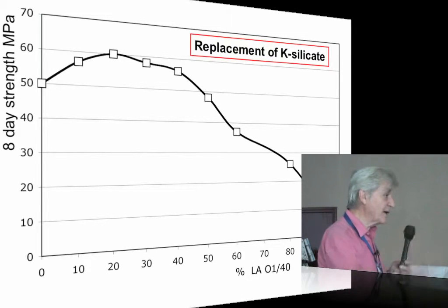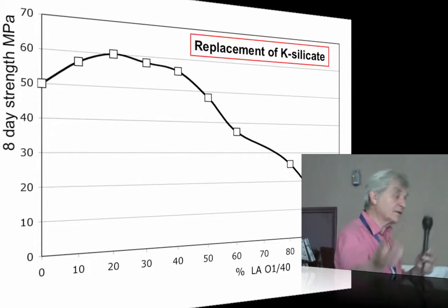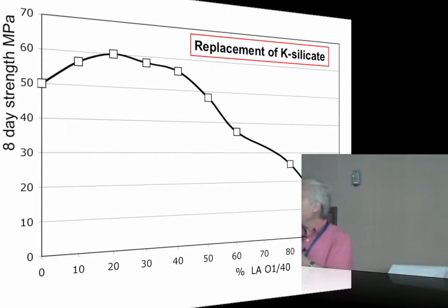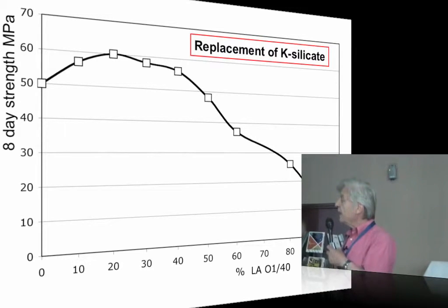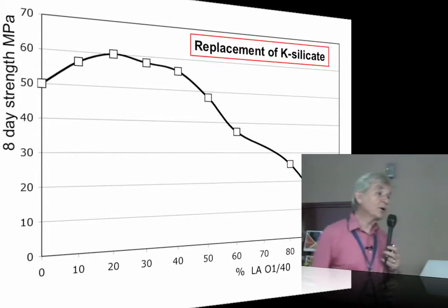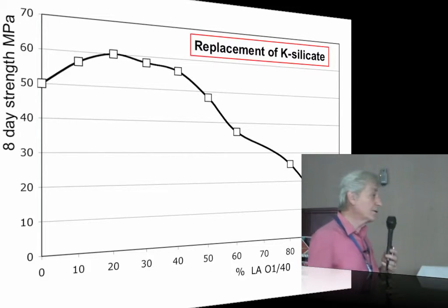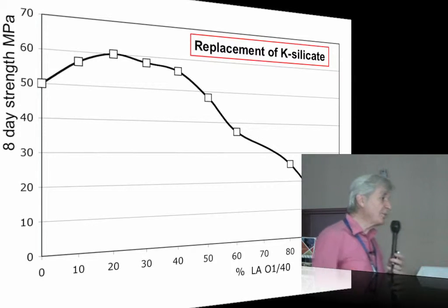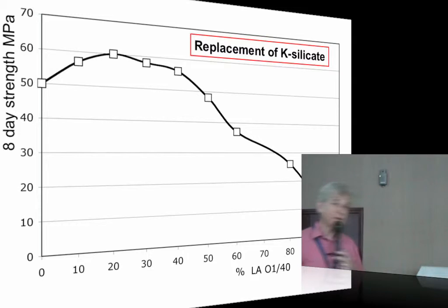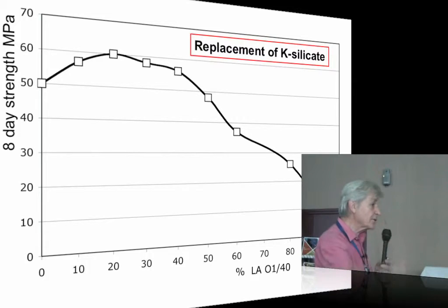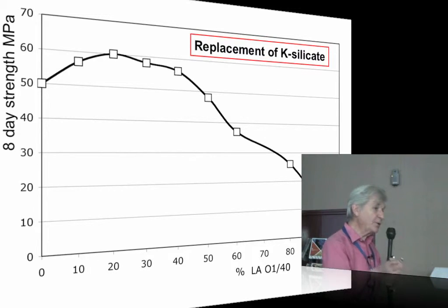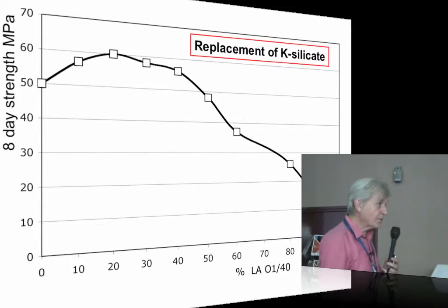Which means our basalt must be activated. So, this is alkali activation of the basalt, so that it starts to react, it starts the chemistry. And up to now, we need to add a small amount of potassium silicate. So instead of having 10% of the bulk, we only have 2%. This is better. This is just a study. It is not the result of an industrial process. It is just a way to show that this is possible.